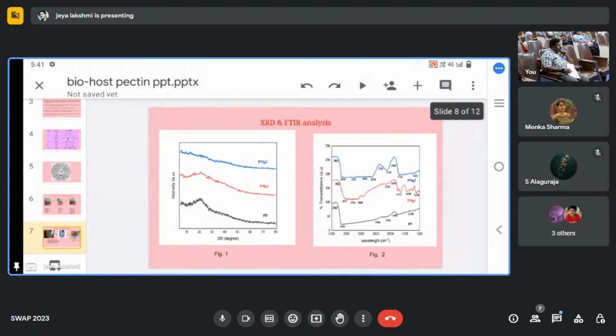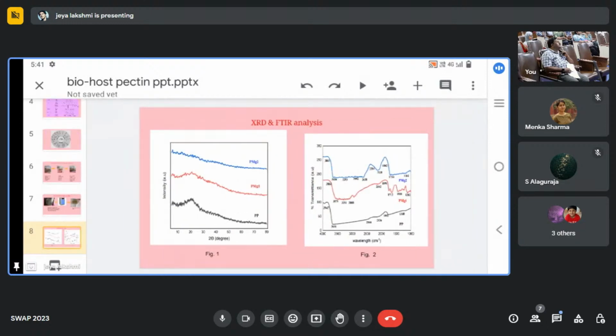Then that solution is poured into a petri dish and placed in the oven at 50 degrees Celsius. After drying, we obtain the freestanding thin film, and this is the thin film I obtained, which is shown in the picture. From this slide, we move towards the characterization studies.